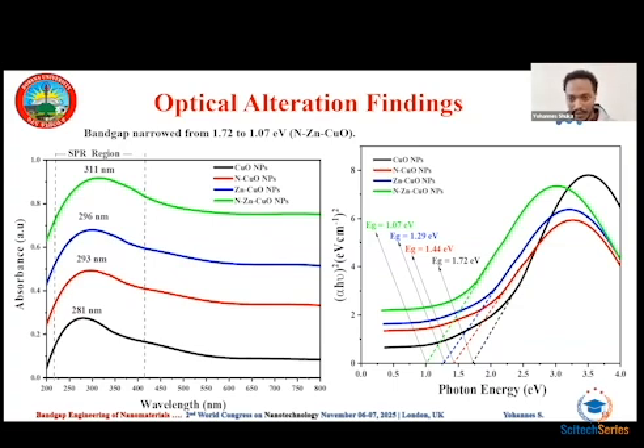And here you have another picture that indicates the bandgap engineering of the materials. As you see here, the bandgap for the pure copper oxide nanoparticle is 1.72 electron volts, which is the maximum bandgap. And after applying some modification of the primary material, the bandgap for nitrogen-doped copper oxide nanoparticle is reduced to 1.44 electron volts, and by modifying the copper oxide semiconductor with zinc, the bandgap is reduced to 1.29 electron volts, and by co-doping, that means by incorporating nitrogen and zinc, the bandgap of the material is decreased to 1.07 electron volts.